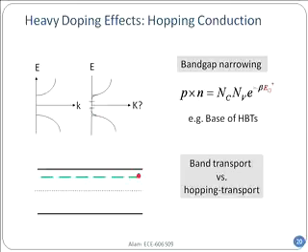But at the very least, you should know this because it's very useful and relevant for the devices that we are presently interested in. In fact, your flat panel displays, the things that you go buy, this 46-inch, 52-inch, each one of the pixels is driven by transistors that are most of the time made of amorphous silicon, which doesn't have a crystalline property. And in that case, transport could often be through hopping transport. The organic electronics also use hopping transport. So lots of parts of electronics is actually being governed by this type of transport through the localized states.